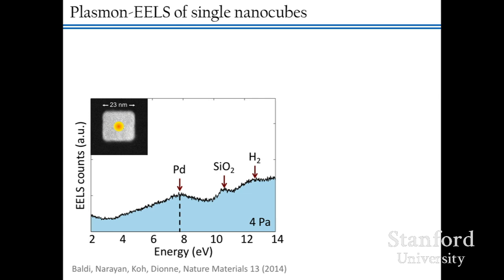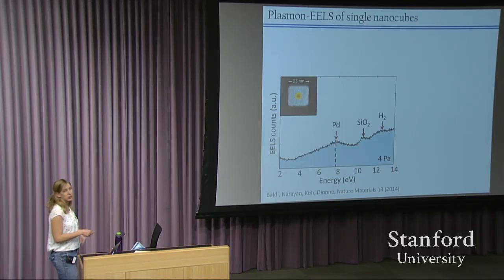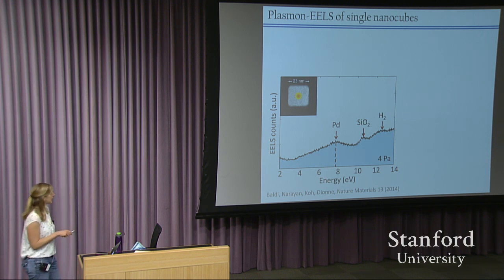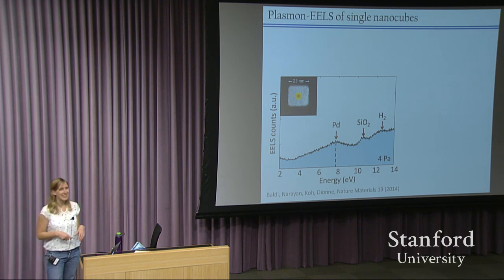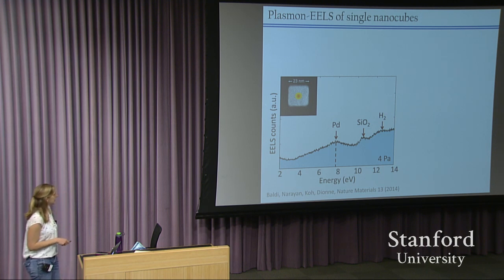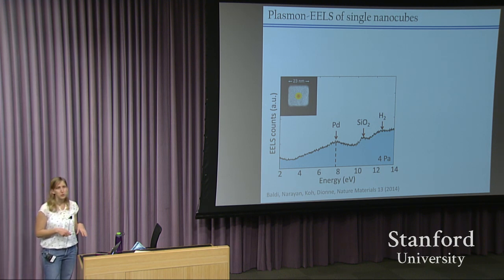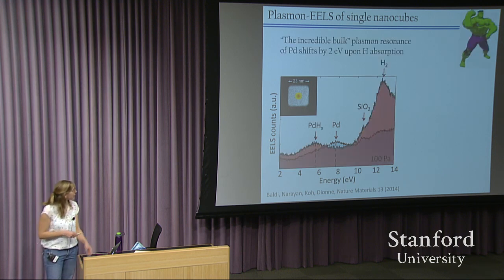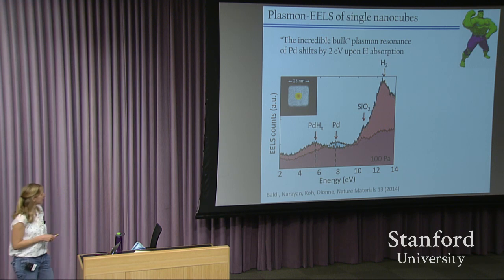And when we have no hydrogen or very little hydrogen in the environment, here we just have a pressure of 4 pascals around the nanoparticles, we find a spectra that has a number of peaks, one of which corresponds to a little bit of hydrogen in the environment, that's at about 12 electron volts, one of which corresponds to our silicon dioxide substrate on which we've placed the nanoparticles, and then we have another peak at 8 electron volts that corresponds to palladium. And I like to refer to this peak as the incredible bulk plasmon resonance.